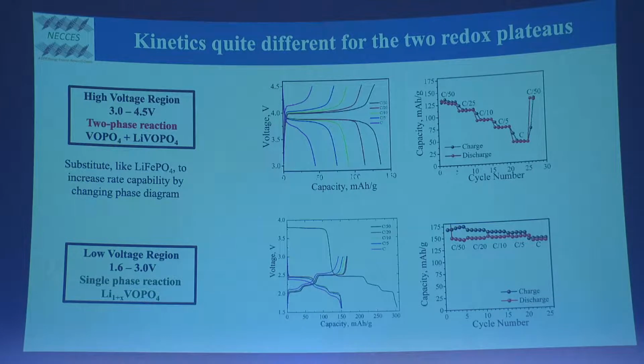And our structural studies said we have VOPO4 plus LiVOPO4, so we have a 2-phase reaction. So right now we're trying to change that. In contrast, vanadium 4 to vanadium 3, that's this curve in here. So to make this, we charge down here, put 2 lithiums in, then just cycle at a lower voltage.